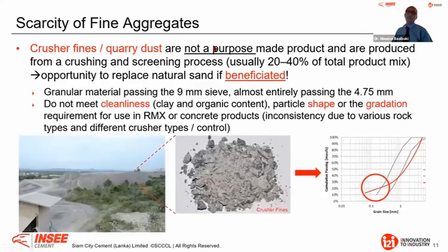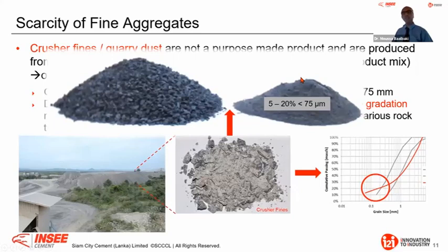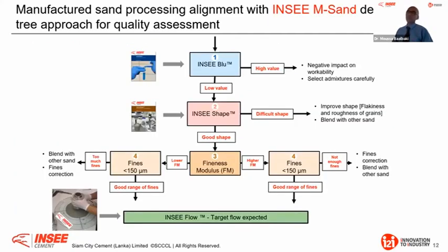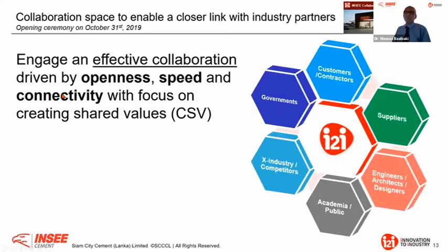At the same time, when it comes to scarcity of raw material, we discussed these topics about two or three months ago: very often what we call manufactured sand is not a purpose-made product. It is really crushed fines or quarry dust, compared to natural sand. Very often these have a very high amount of fines, with inconsistency that can go from 5 to 20% passing the 75 micron. And as they are crushed, they don't have a favorable shape. Therefore, we have developed and presented to most of you a very holistic approach on how to tackle different quality indicators to achieve performance, for example in terms of flow and compressive strengths, using those products. All that has been introduced in our I2I.